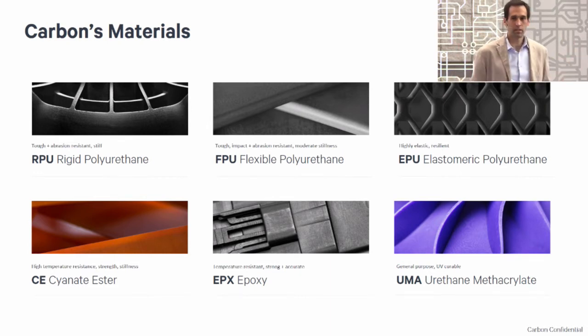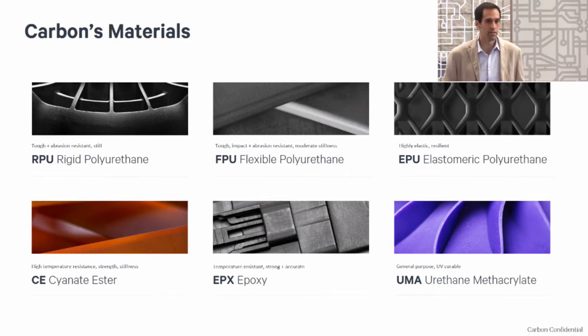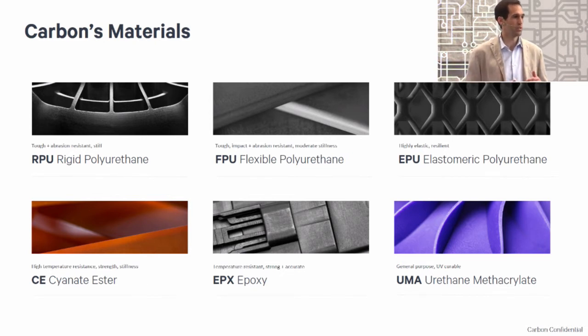So we have six families of materials today, which you can see over in our booth. The six families include a rigid polyurethane, which behaves very much like an injection molded ABS material. It's a tough material, it's abrasion resistant, it's stiff. We have a flexible polyurethane that behaves very much like a polypropylene. It's much more flexible than a rigid polyurethane. And our elastomeric polyurethane is the parent of what you see with the Adidas resin. So the Adidas resin is a derivative of this family of resins, and it's a rubber type material.